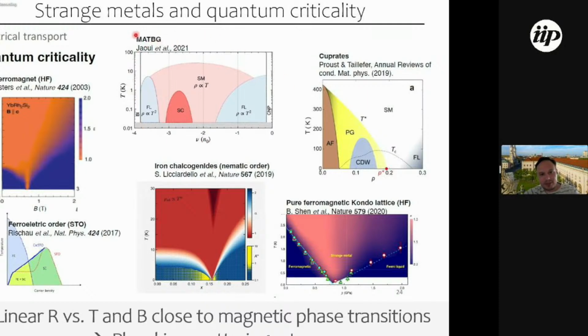In the end, I will show this phase diagram in more detail. But if you look at this phase diagram, which we have found in magic angle twisted bilayer graphene, and compare it, in a very naive way, to the phase diagrams which people found in the cuprates, in Kondo lattice systems, and iron chalcogenides, in ferroelectric materials like STO, and also in antiferromagnetic materials, they all have in common that there are often superconducting states very close to some sort of ferromagnetic or antiferromagnetic phases.